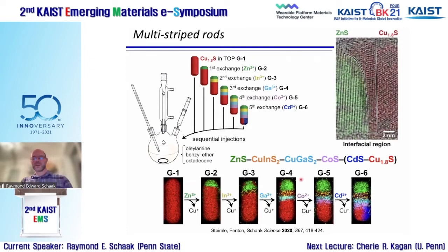So all of this is rational and predictable in the sense that we're choosing the order based on the injection sequence, and we're defining the orientation of the interfaces based on those crystal structure relationships. And so one reaction ends up forming a sixth generation rod that's zinc sulfide, copper indium sulfide, copper gallium sulfide, cobalt sulfide with a cadmium sulfide, copper sulfide kind of dimer segment at the bottom.